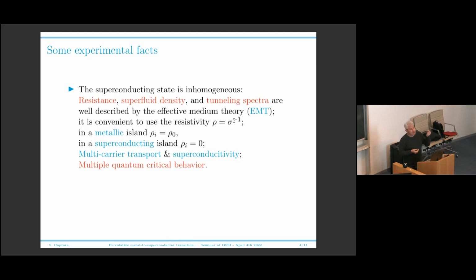Why? Because the resistivity is zero in the superconducting state, whereas the conductivity is infinite. So, not to have infinities around, you may change your variable from sigma to resistivity, which is nothing but sigma to the minus one. So we are going to assign to a metallic island a resistance, which is a constant. You can think of this constant as the resistance in the metallic state.